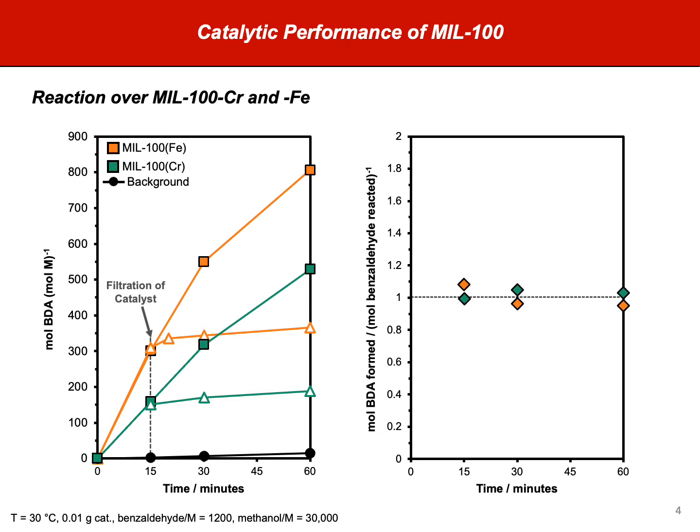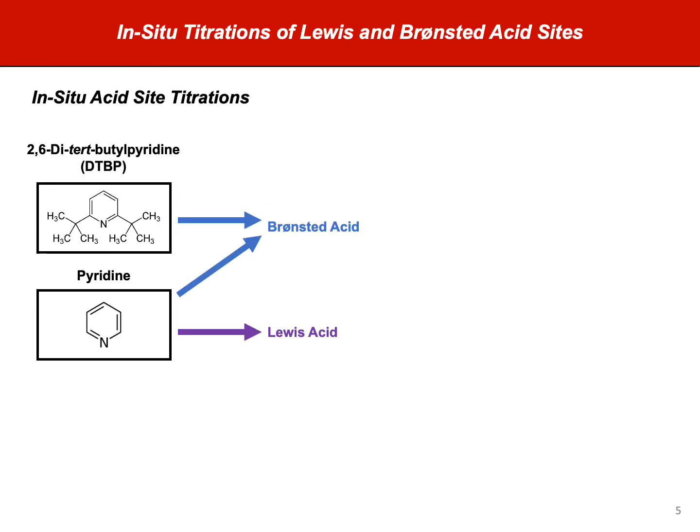Another quick check before we go on to our titration data. In order to make sure that the catalysis does originate from the heterogeneous catalyst and not from leached species in solution, we carried out a filtration test where the filtration was carried out at 15 minutes. And noting that the residual activity after filtration corresponds closely to the activity that was measured without a catalyst, we at least have some level of confidence claiming that the acetalization activity originates from catalysis over the actual MIL-100 framework and not from leached species in solution. Now let's look at the titration data.